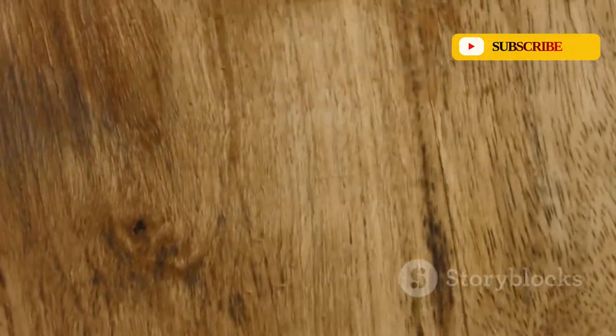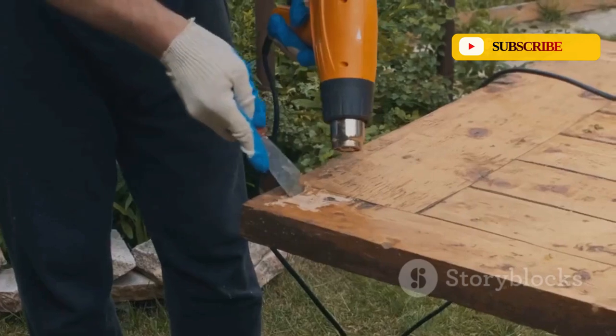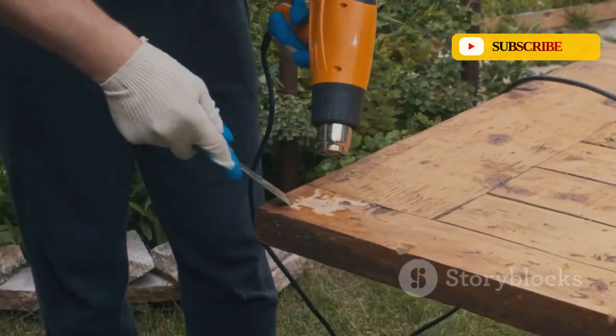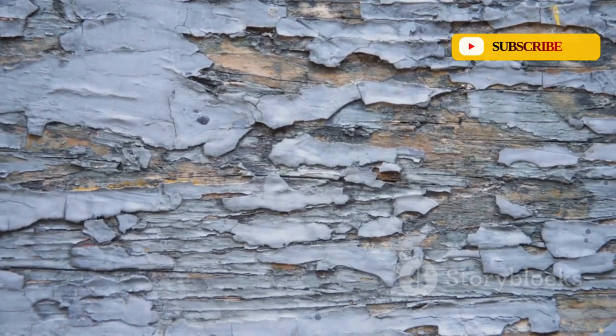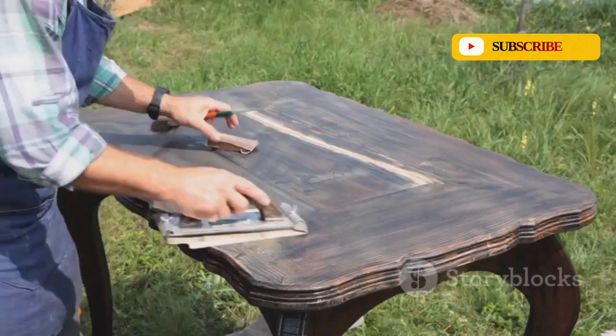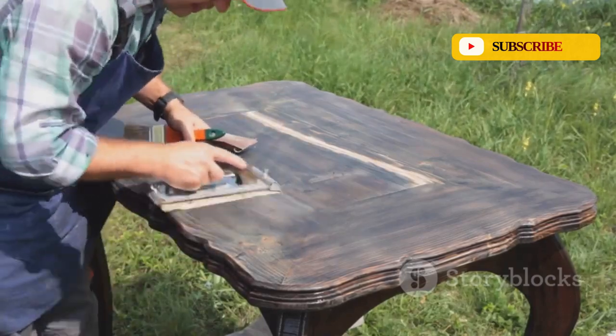A tabletop that was once pristine now has a cloudy, milky patch where a sweaty glass sat for too long. Moisture gets trapped underneath the polyurethane, unable to escape, and the finish fogs up like a bathroom mirror. Or worse, you see the edges start to lift and peel. It looks like a bad sunburn, with flakes of plastic sloughing off, exposing the vulnerable wood beneath. This isn't protection, it's a temporary illusion.